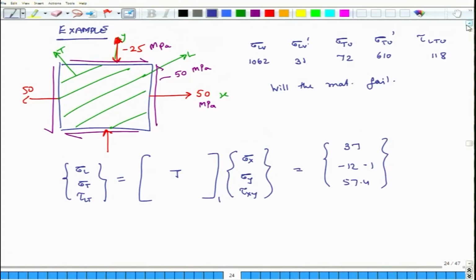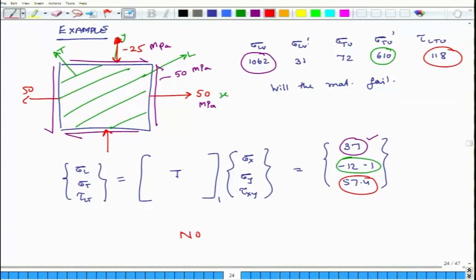So, now we compare whether any of these values is exceeding its limit. First we see 37 and we compare it with 1062. It is not exceeding, so this is okay. The second number is 12.1, but it is negative, so we compare minus 12.1 with 610, and again it is not failing. The third one is 57.4, and we compare it with the shear strength of the material, and again it is not exceeding. So, all the conditions are met. No failure. There will not be any failure. This is how the maximum stress theory works.